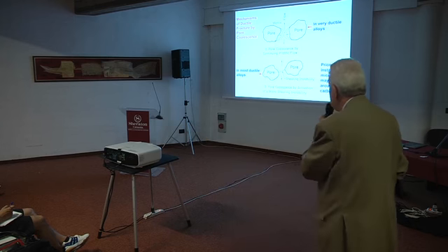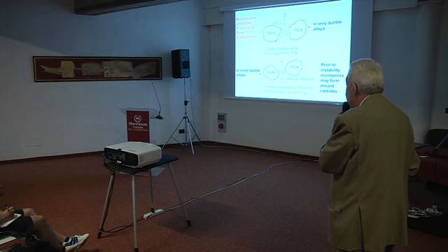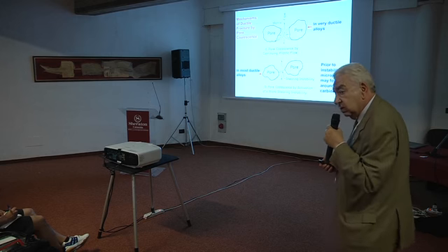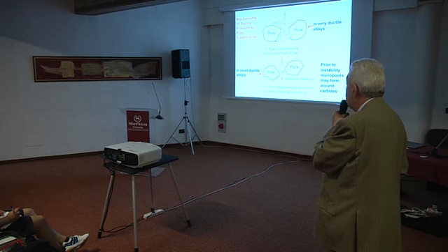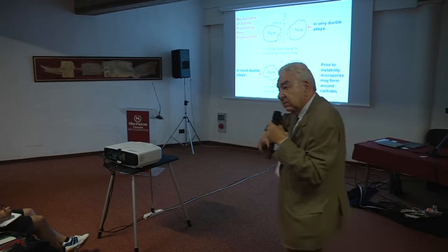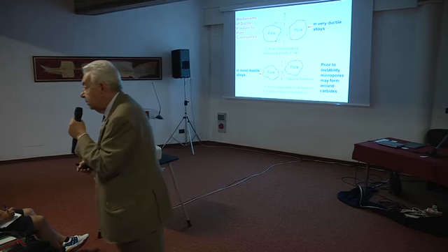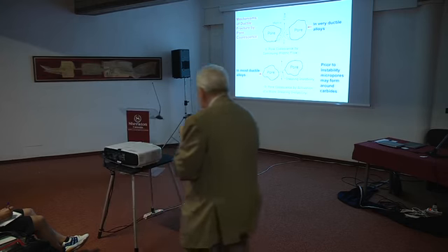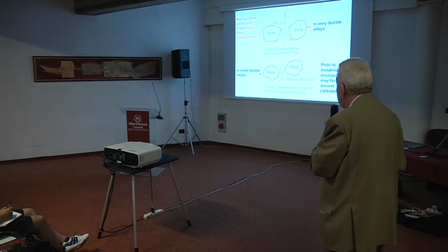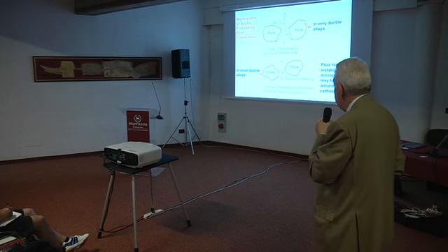And this is the limiting case of ductility. Think of the amount of energy that goes into this type of mechanism, because it deforms and deforms and deforms, the pores enlarge, enlarge, enlarge, up to a single point. But this is only in the case of very, very ductile alloys.